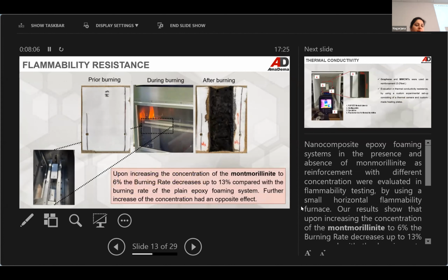Okay, the first property that we wanted to investigate was the flammability resistance. This is of particular interest in the automotive industry, since these foams can be used in cars or in seats, etc. We have seen that by increasing the concentration of montmorillonite nanoparticles to 6% weight, we have managed to decrease the burning rate by 13%, which means that incorporating these nanoparticles hinders the burning rate and causes these materials to be more resistant to flames.